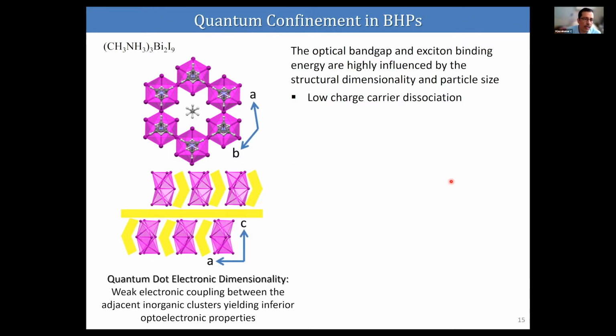So we made the most common methyl ammonium bismuth iodide, and you can see a strongly quantum confinement structure in this material. You can see the yellow one is the inert atmosphere created by the methyl ammonium. So there is no continuity, no electronic coupling is possible between the inorganic clusters, and that is yielding very inferior optoelectronic properties in this material. Of course, it is difficult to go to 3D structures with the bismuth halide materials.